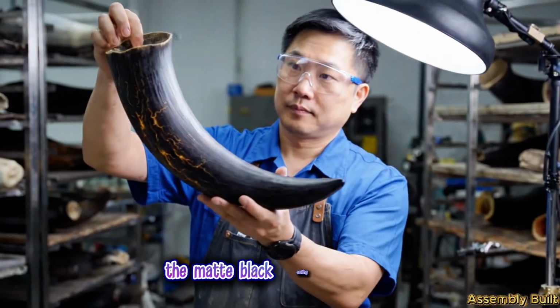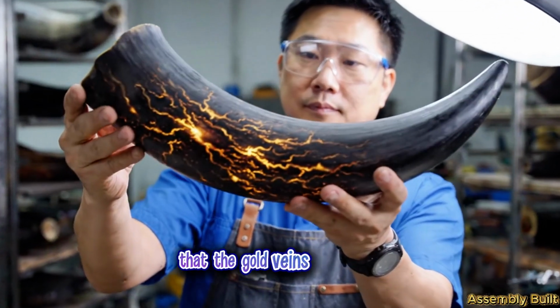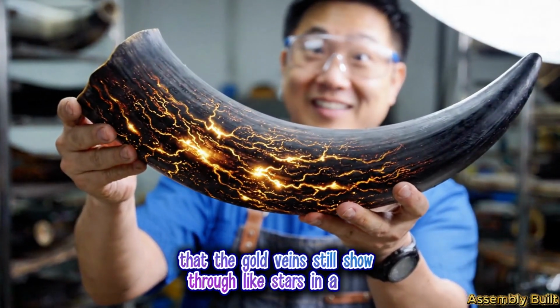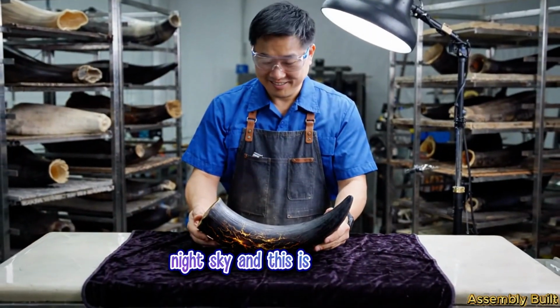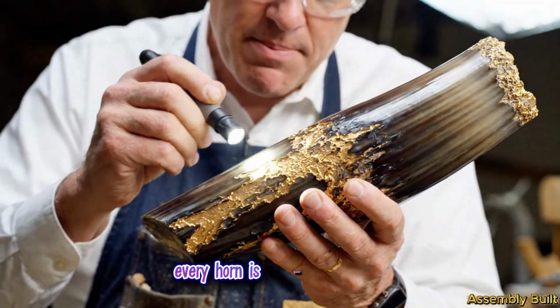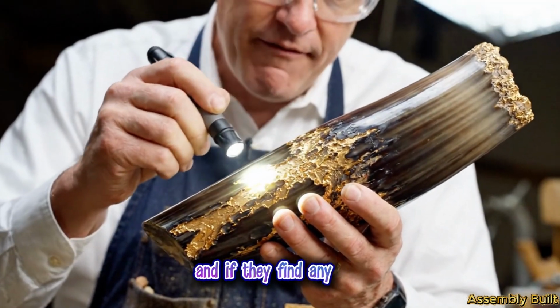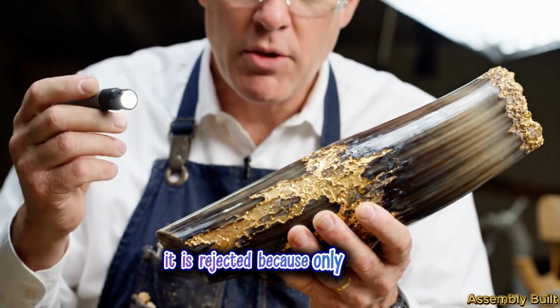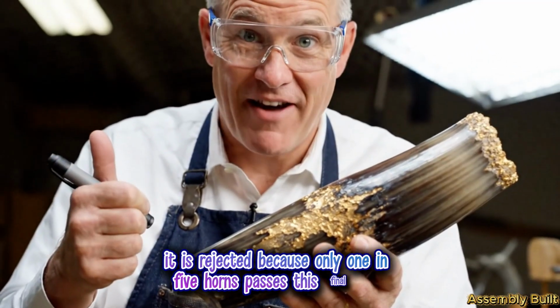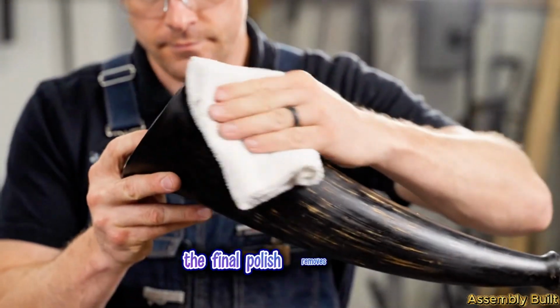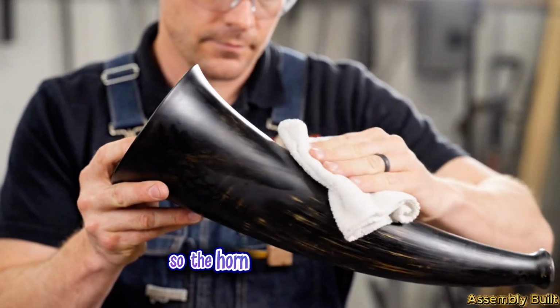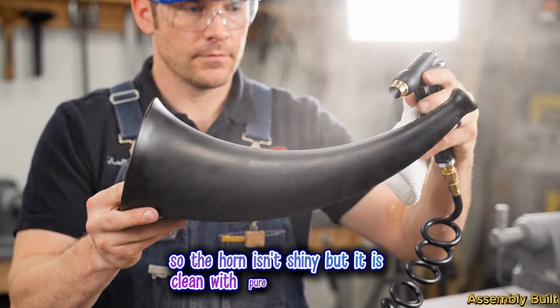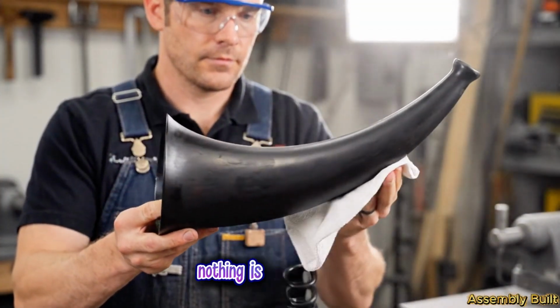The matte black coating is so thin that the gold veins still show through like stars in a dark night sky, and this is what they came for. Every horn is inspected by hand, and if they find any flaw, it is rejected, because only 1 in 5 horns passes this final test. The final polish removes any microscopic dust so the horn isn't shiny, but it is clean with pure matte perfection. Nothing is left to chance.